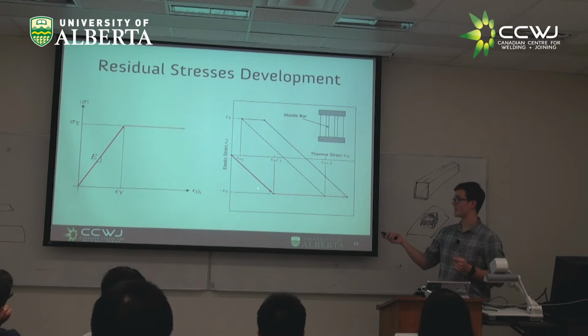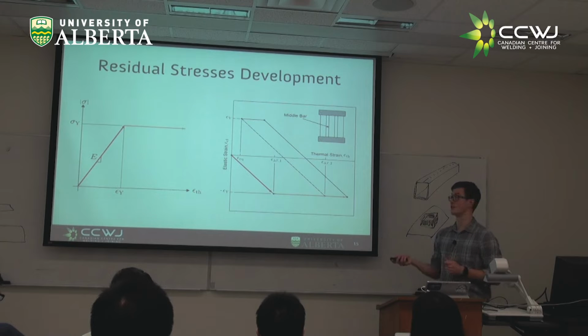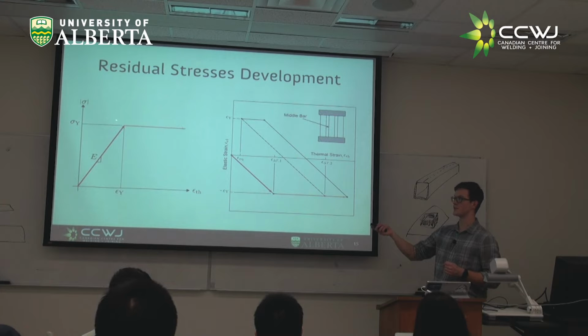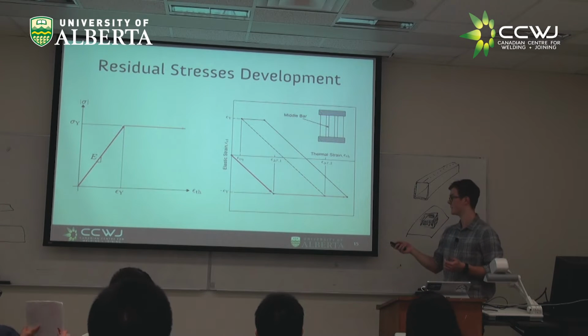Now, alternatively, you might go up to some really high peak temperature. So high that you have all this extra strain that's beyond what was the strain where you started to yield. Now, if you imagine this strain is the same as this strain, what would we call that amount of strain in a stress strain curve? So this is our elastic strain. What would this be? Plastic strain. Right. So all of this strain we've exceeded our yield point by is the plastic strain.